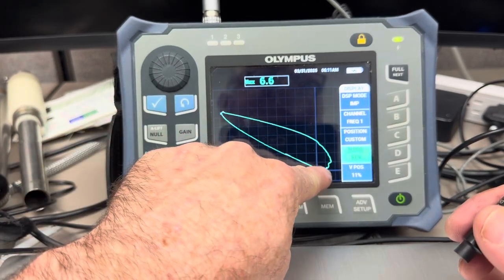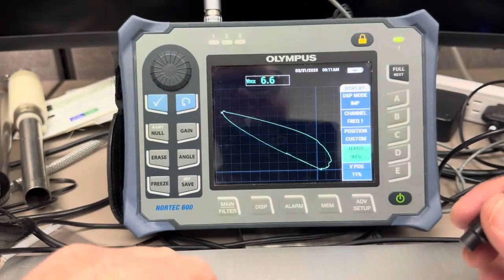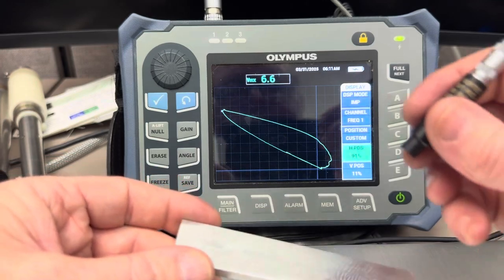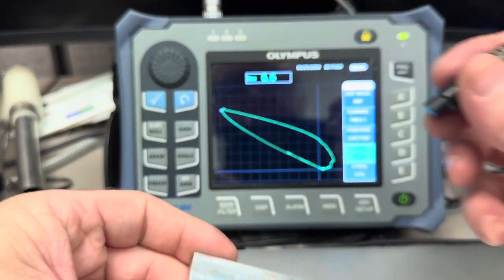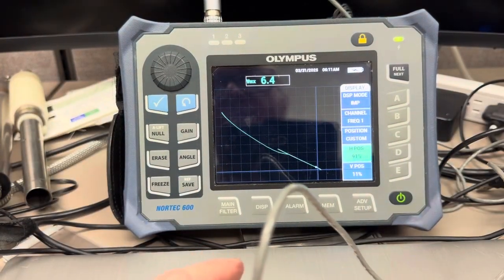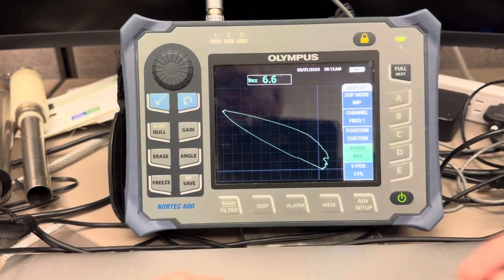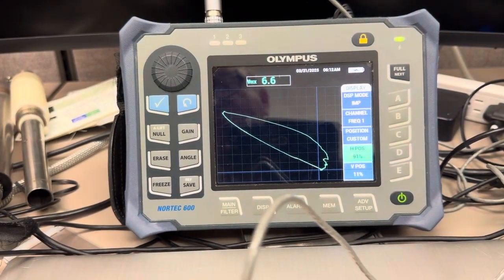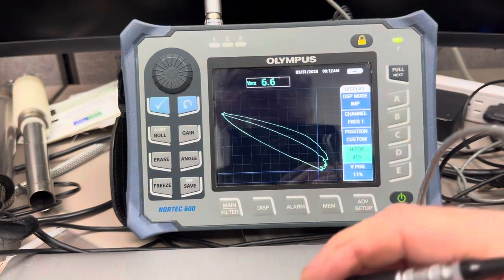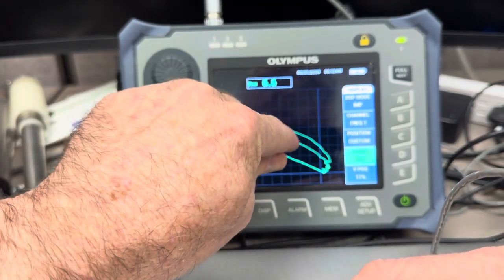This is infinitely thick material, and that's our air point, high inductive reactance. But now what I'm going to do is, instead of sliding down towards the thinner end, I'm going to go on the thick end and move my probe laterally to the edge. That's our liftoff. That's our thinning curve. And now I'm going on the thick end towards the edge, and you see a different trajectory. So that line in between the liftoff line and the thinning curve is the edge effect curve.